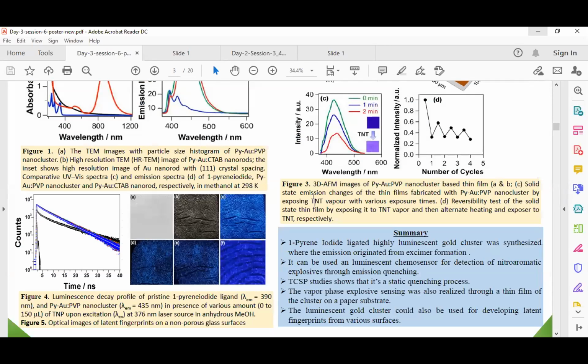So this is my summary. Pyrene iodide ligated gold cluster was synthesized and originated from excimer formation. It can be used in luminescence chemosensor for detection of nitroaromatic explosives through emission quenching. I have shown the TCSPC. Then for vapor phase explosives, I have shown the thin film data above, so here you can see the quenching sensing is done.